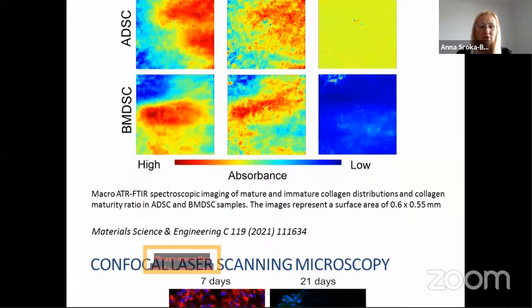Our results based on ATR imaging were also confirmed by confocal laser scanning microscopy. So we used another technique to confirm our study. Type 1 collagen was here in the left column, and in the right column we have osteocalcin, which confirmed that the cells really grow on the biomaterial surface. So those are the examples and confirmation of our technique.